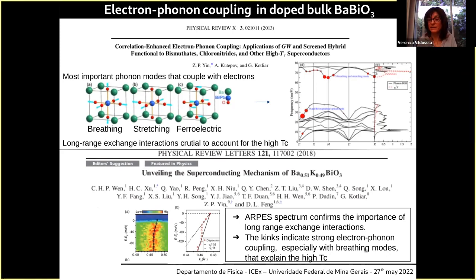So the phonon modes that were operating in this material were the breathing distortions that, as I already described, the stretching distortions that are like the breathing ones but two-dimensional, and the ferroelectric distortion. These 3 modes contribute to the electron-phonon coupling that explains the high TC superconductivity in this material in the bulk form.